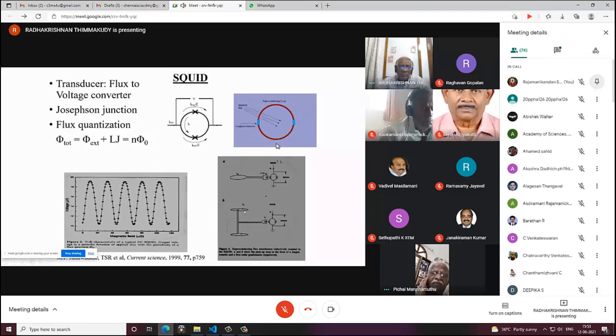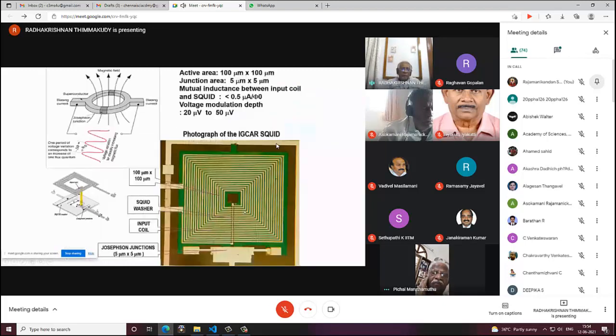Now, the SQUID we also set up elaborately as a micro device. The reason is the SQUID cannot be very big. The Josephson junction cannot be very big because I don't want to go into the parameters of the SQUID, but essentially 2 or 3 things have to be there. All the SQUID parameters, the energy coupled has to be much less than kT, the temperature. So that's why you go to low temperature. And that also means critical current, everything has to be low. That means size has to be small.